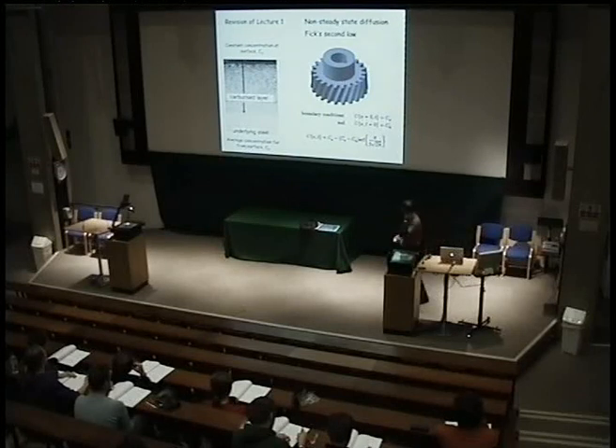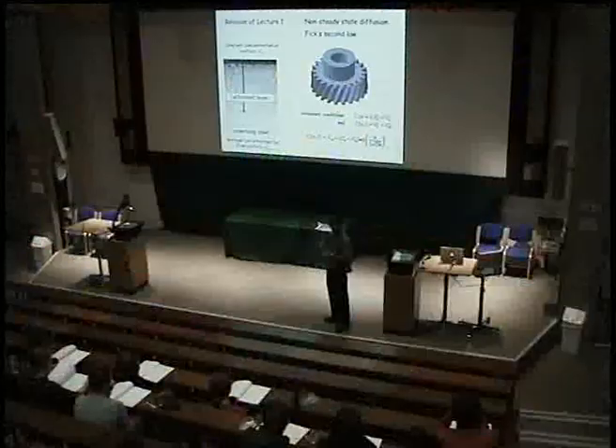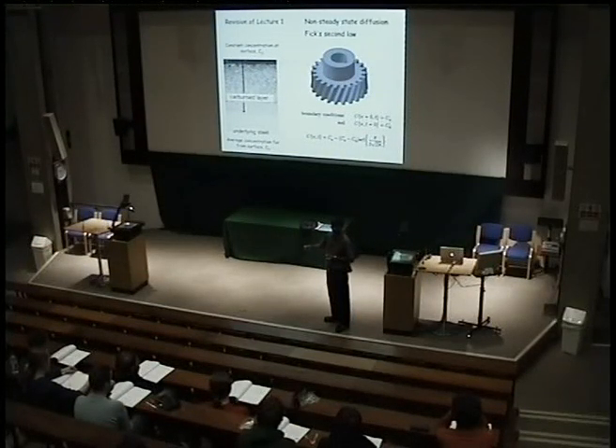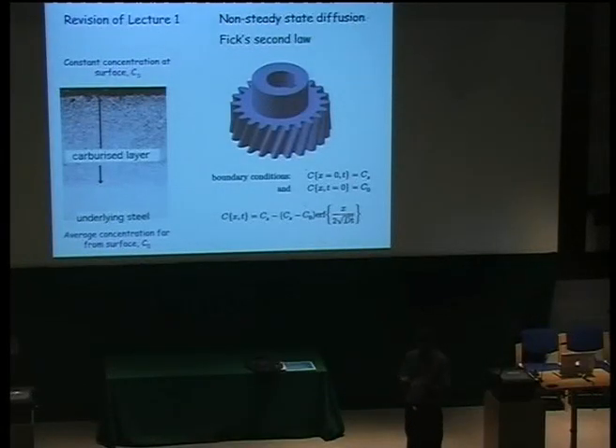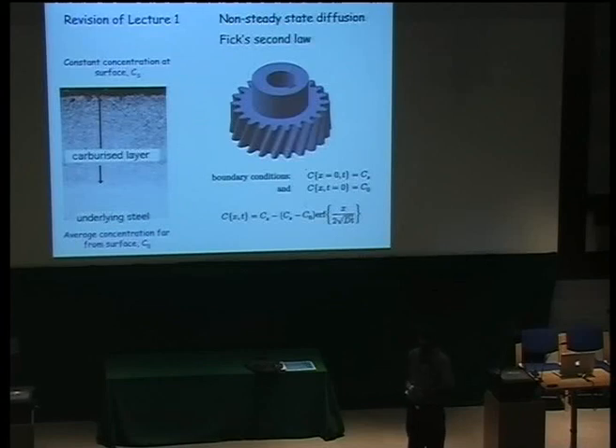By contrast, here is a very important industrial example — a particular gear. Gears mesh with each other, rub against each other, and there are huge contact stresses. The core of the gear has to support stresses and sudden knocks, so it must be extremely tough. On the other hand, the surface needs wear resistance — it must be extremely hard. So what we do is diffuse carbon into the surface by maintaining a constant carbon potential using a gas mixture on the outside, heating it up so diffusion is rapid, and allowing carbon to diffuse into the surface, which hardens it.